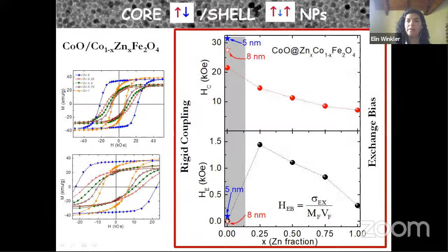So going to the magnetic results, we observe that when we systematically increase the concentration of zinc, the hysteresis, the coercive field, is systematically reduced, which is drawn here. And remember, in the previous system, we have a very large coercive field and zero exchange bias. And when we replace a little of cobalt by zinc, suddenly we observe an asymmetry of the hysteresis cycle, and then it's systematically reduced. Why? Because we are reducing the exchange interaction at the interface.